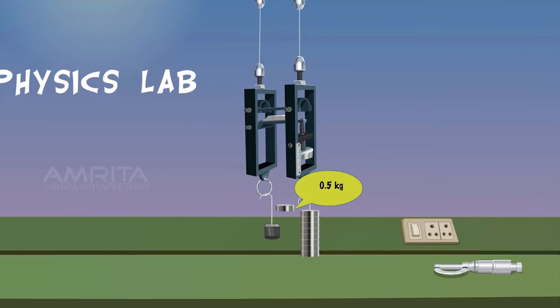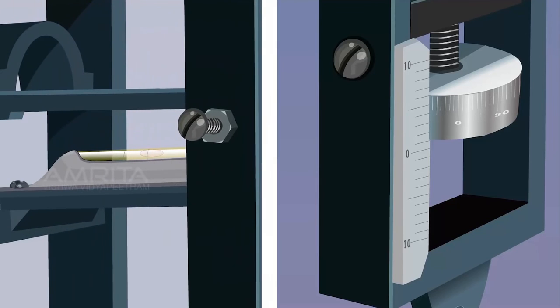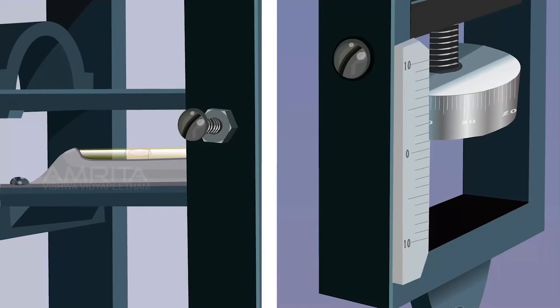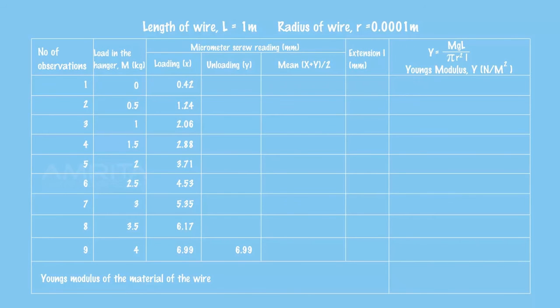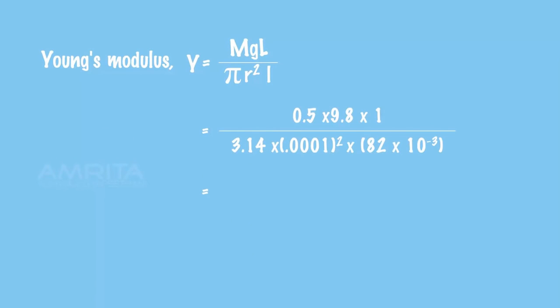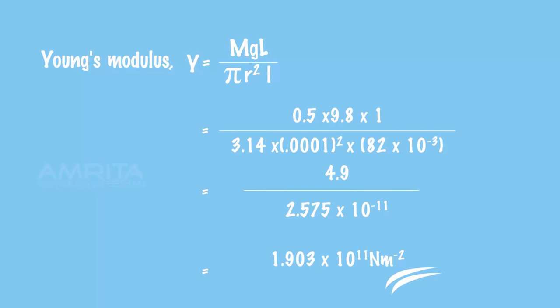Remove a weight from the weight hanger. The bubble now shifts to the right. Fix it at the center by adjusting the central screw and note the spherometer reading. Repeat the experiment by removing weight in equal steps of 0.5 kilogram and record the observations. Calculate the extension produced each time and then find the Young's modulus. The mean of the calculated values gives the Young's modulus of the material of the wire.